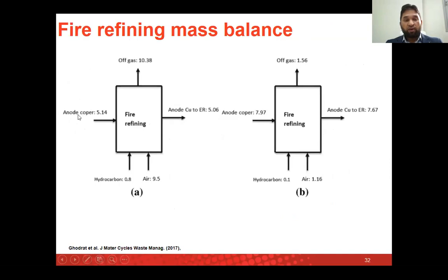So the next step is fire refining. We have an anode grade copper that goes into the fire refining process. What we do in fire refining, again, is inject some hydrocarbons and air, and we make some off gases. And why do we do this? We do this to remove the last bits and pieces of lead, zinc and tin that are still in the anode grade copper, to increase the purity of the copper.